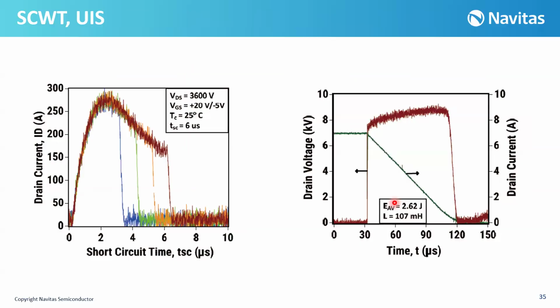Here is the short circuit withstand time and UIS capability for these 6.5 kilovolt devices. The VDS for short circuit withstand time is 3.6 kilovolts with a VGS of 20 volts and minus 5 volts at room temperature. If you look at the data, we can see a high short circuit withstand time of 6 microseconds. And finally, for the UIS capability, here is the drain voltage. We can see a high peak between 7 to 9 kilovolts before the failure, and the peak current reached around 7 amps before the failure, with avalanche energy of 2.62 joules. So we have a high capability of the UIS.